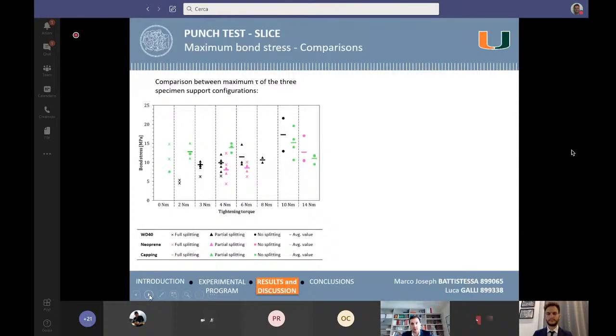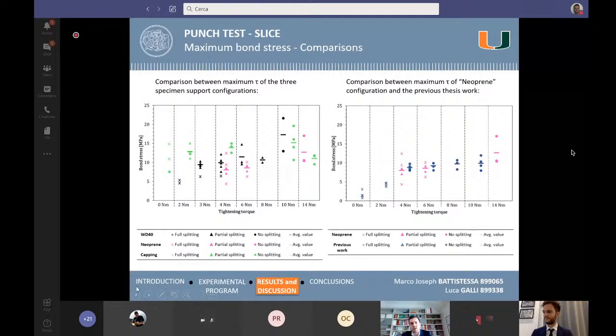A drop of values was recorded in the splitting displacement, and when no splitting occurred, no matter the configuration we used, we have identified similar bond stresses. And this trend was also confirmed by the results of the visual analysis. The difference in the tightening torque applied, therefore, may be related to the specimen support configuration. In fact, in case of capping, an additional confinement action is provided by the support system itself, thus explaining the lower tightening torque needed.